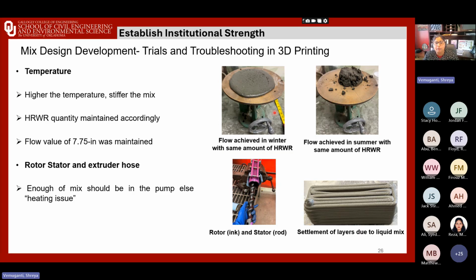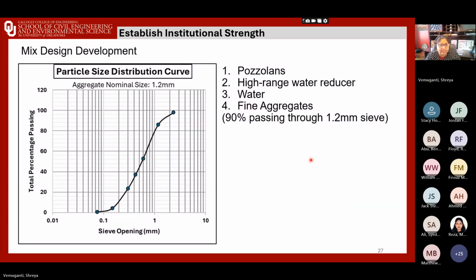And in this one, the pump wouldn't be clogged, but we had problems with settlement of layers due to too liquid of a mix. So this trial and error approach taught us how sensitive the mix is to small changes in temperature, in dosage, like the pozzolans itself, and also, of course, water content. So our final mix essentially had pozzolans, high range water reducer, water, and also fine aggregates, which are 90% passing. I am not mentioning the exact ratios here. Our final report also has that.